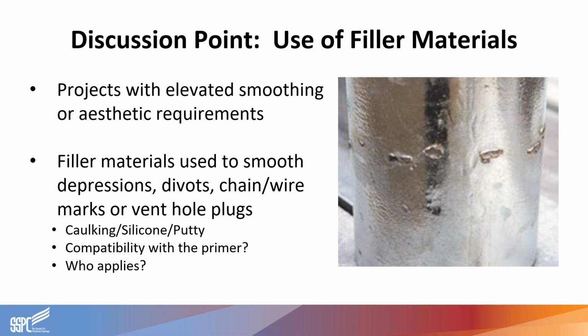Sometimes these are pushed in a little too far, and there can be a discrepancy in the height of the coatings there. I see this most often on projects that have elevated smoothing or aesthetic requirements, such as architecturally exposed structural steel, but in general, also other project types of high visibility. If you're looking to achieve a smooth, paintable surface in these areas, you may need to specify a filler material that the galvanizer or painter can easily apply.